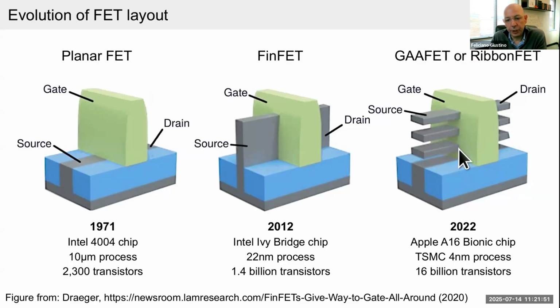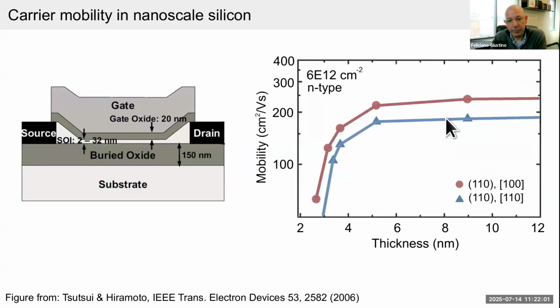So why am I showing you this? In order to go from the left to the right, the thickness of these layers has been going down in order to allow for lateral scaling. And this poses a problem. These are very old experiments that are considered a classic in the field. What people have done is to study the mobility, basically the transport of electrons, as you thin down this channel. And these are the results.